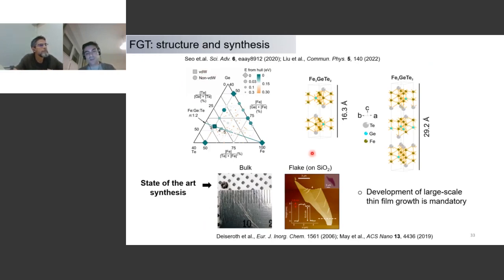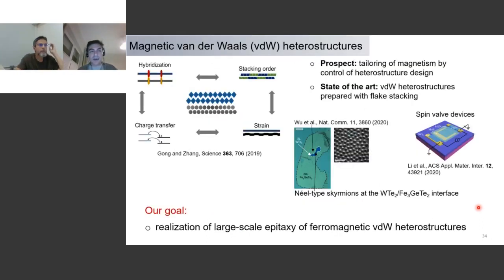And in terms of synthesis, again, similar to other 2D materials, the state of the art is bulk crystals that are very tiny, and when you exfoliate flakes out of that, they are also micrometer size, not bigger than that. So again, same story: development of large-scale epitaxy is mandatory. And of course, combining that with other 2D materials would allow creating another tuning knob for controlling magnetism, while you have this interface between different 2D materials where you could have different types of effects that would allow you to modulate magnetism.